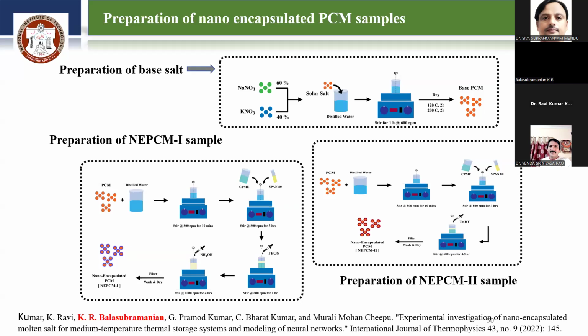Then the CPME and SPAN 80 will be mixed in, and it has to be stirred for 3 hours with these mixtures. Then TEOS will be added, and once again it will be stirred for 1 hour. Then NH4OH will be added, and it will be washed with distilled water and filtered. Then we will get a nano encapsulated PCM. Basically, the base PCM will be there, over which the coating is done. That is the nano encapsulation. So that is one method.